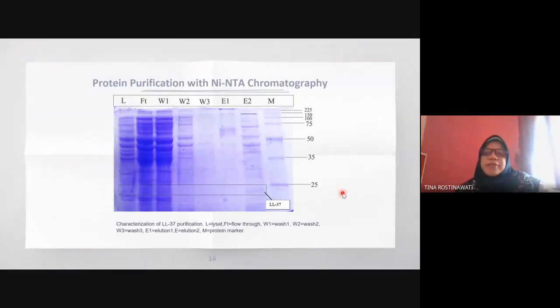The last, we do the protein purification with Ni-NTA affinity chromatography. In this slide, we can see that the target protein is not fully pure because there is some impurity protein in the elution fraction. We can see there is some protein band in the elution fraction. So we have to separate these impurity proteins by a strategy using gradient of imidazole concentration. This strategy has been used in our previous research, and the process was successful.